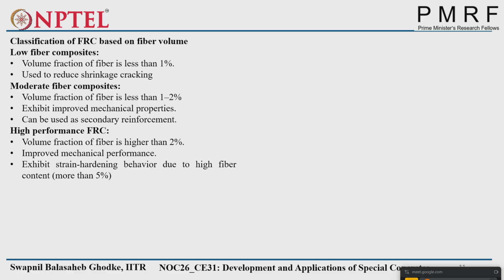In the case of high performance fiber reinforced concrete, if the volume fraction of fiber is higher than 2%, it not only improves the mechanical performance, it exhibits strain hardening behavior due to high fiber content, generally more than 5%. Anyone has any idea about strain hardening and strain softening behavior? We'll see strain hardening and strain softening behavior.